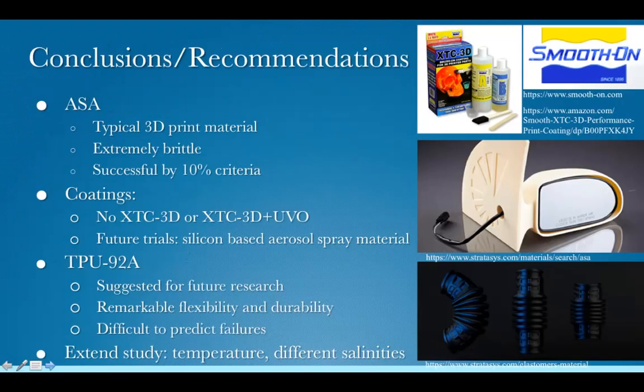Overall, the ASA quantifiably retained its properties within the 10% success criteria, as did the TPU-92A. The XTC3D and XTC3D plus UVO coatings seem to succeed in waterproofing samples, but ultimately are not recommended for further use due to their rigidity and suspected chemical interactions with the ASA. While the TPU-92A was difficult to gather quantified data for, we believe this material shows the most promise for use by the Navy due to its remarkable flexibility and visually demonstrated durability throughout the study. Further testing is suggested to be conducted on fabricated parts to provide more accurate data.